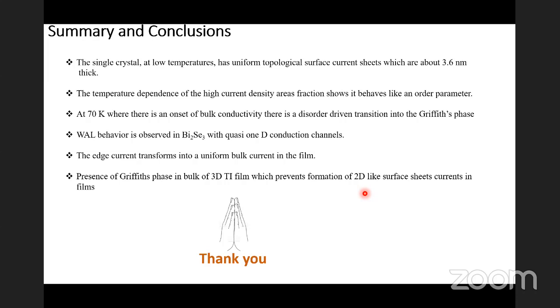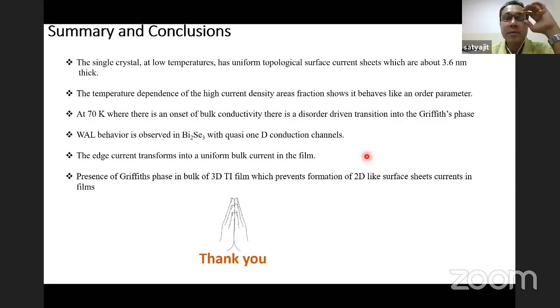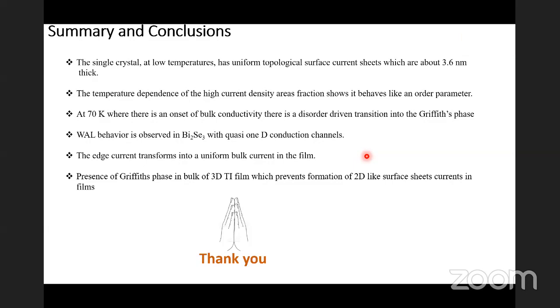transport measurements, even what we did. We did these kind of measurements in samples grown by Nitin Samarth on bismuth selenide, at 10 nanometer thickness. And we saw perfectly two-dimensional behavior, both in weak localization measurements as well as other kinds of measurements. From weak localization, you can easily fit the behavior that you see. You can gate them by applying the strontium titanate gate from the bottom and look at the completely two-dimensional behavior. So I was surprised that you saw a predominance of the edge current. Whether this is a material-specific problem is my question.